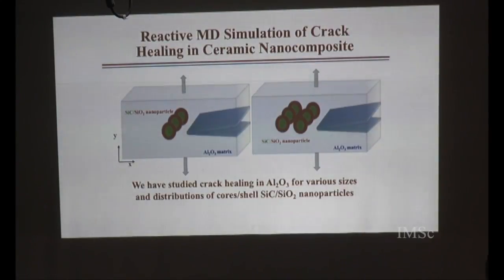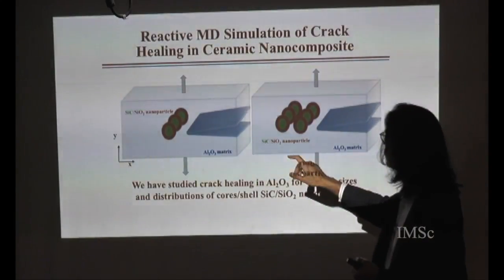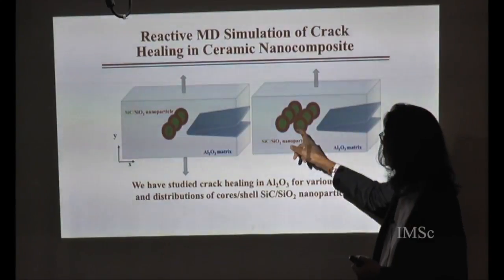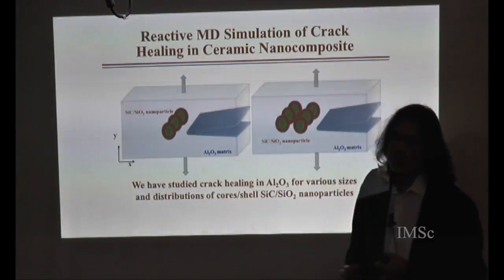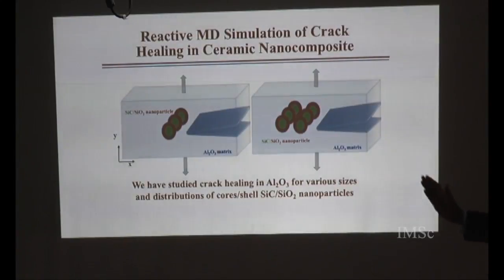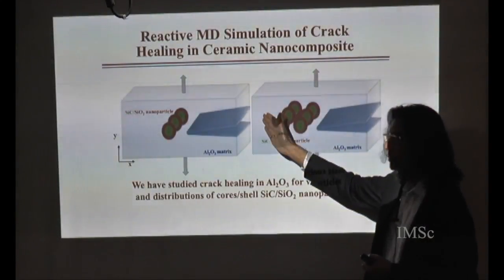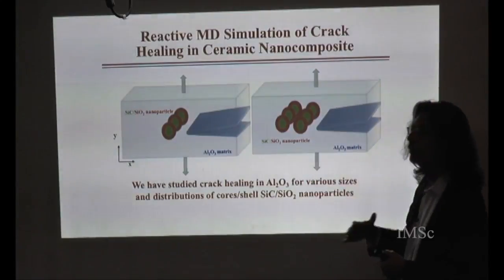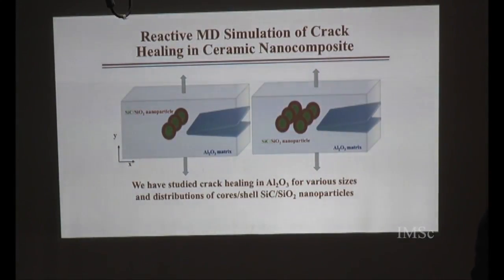Now the thing is, if we actually study silicon carbide oxidation, that's a very long time process. We have done that, but that takes a very long time. So what we did was, we took silicon carbide particles which were already oxidized and embedded them in this alumina matrix. So it's a core shell structure, the core is silicon carbide and the shell is silica. And we have studied this as a function of the number of rows, 1 row, 2, 3, 4. We just wanted to see what happens to cracks in this system.